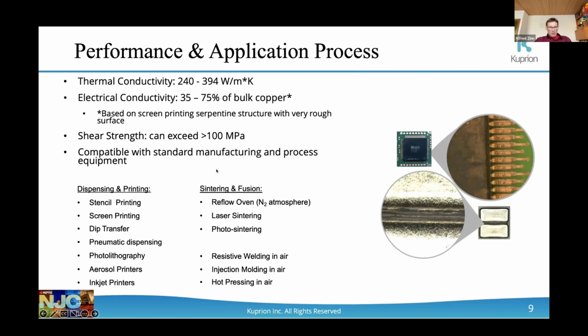And it's compatible with all standard manufacturing as listed here. We have done all of them. It works great. Stencil printing, screen printing, dip transfer, you name it. Reflow ovens, we've done laser sintering, photo sintering. We did some fun stuff with resistive welding in air. I mentioned injection molding for large parts. So these don't require a nitrogen atmosphere. But when you do die bonding of LEDs, for example, you need to do this under nitrogen until the copper is fused to bulk copper. You have to be careful.